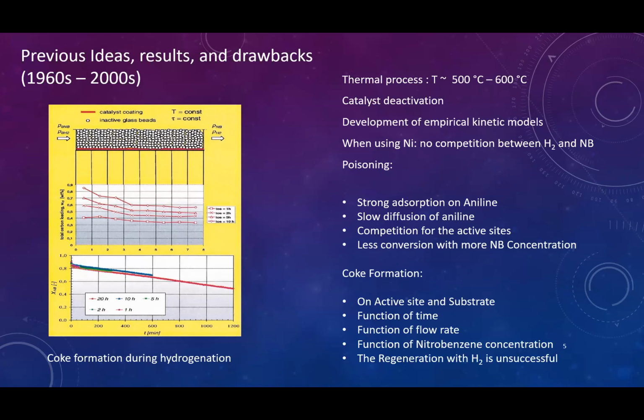To study that, before the 2000s, there was a big development of empirical kinetic models. Many people used different catalysts. As an example, when using nickel, they showed that there's no competition between the adsorption of hydrogen and nitrobenzene. So they found two major pathways for deactivation of the catalyst. First, the poisoning. There's a strong adsorption of aniline and a slow diffusion of aniline outside of the catalyst structure. Then this creates a competition for the active sites between nitrobenzene and aniline. And also, when we increase the concentration of nitrobenzene too much, the conversion decreases and we have less selectivity.